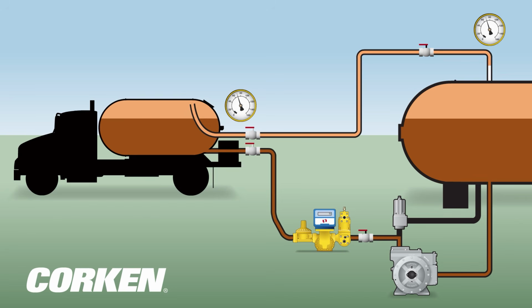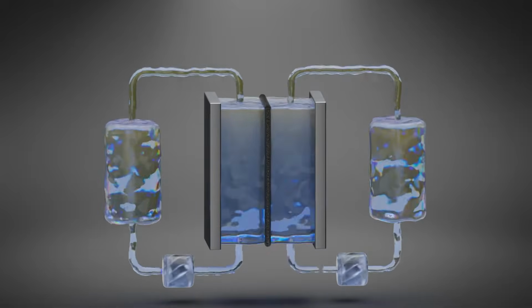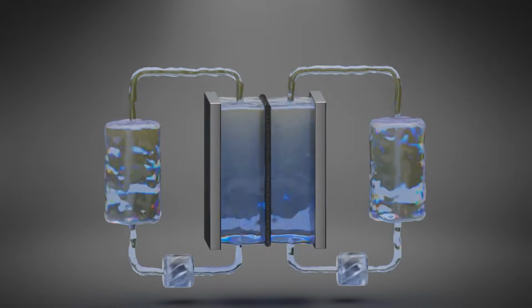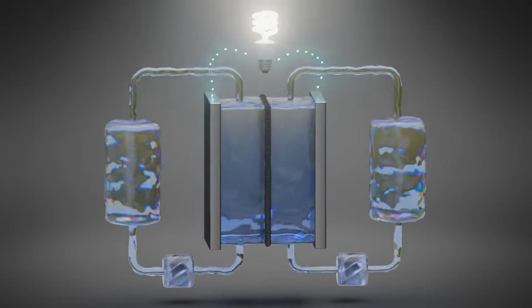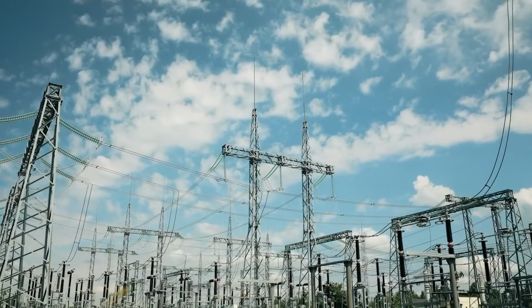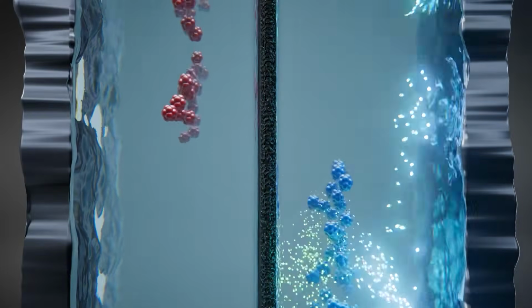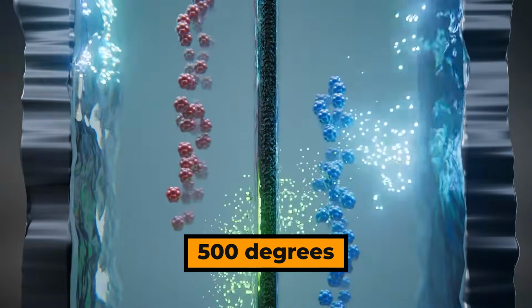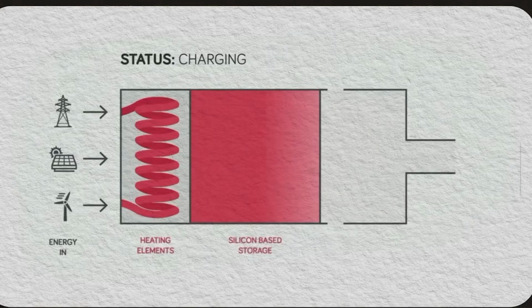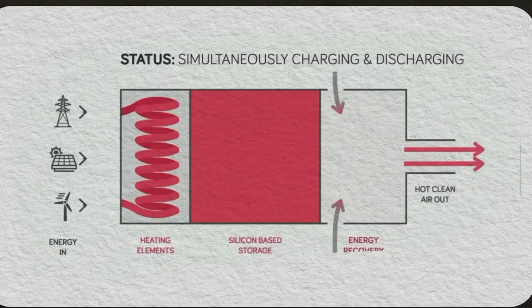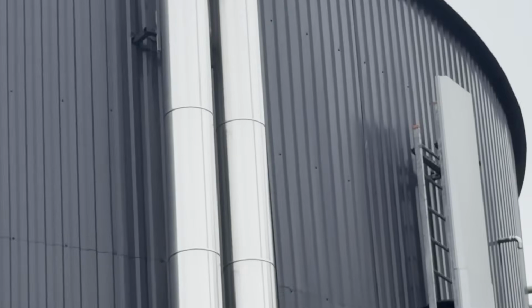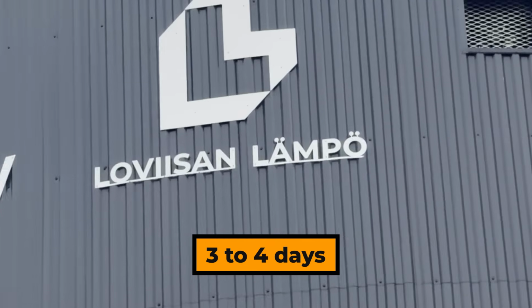The property that makes sand so effective for this role is its specific heat capacity, combined with its tolerance for extreme temperatures. Sand stores approximately 830 joules of energy per kilogram per degree Celsius. Here is what that means in terms you can use. 1 metric ton of sand, heated to 500 degrees Celsius above ambient, holds roughly 115 kilowatt hours of usable thermal energy. That is enough to keep a well-insulated 1,500 square foot home warm for 3 to 4 days in US Climate Zone 6.